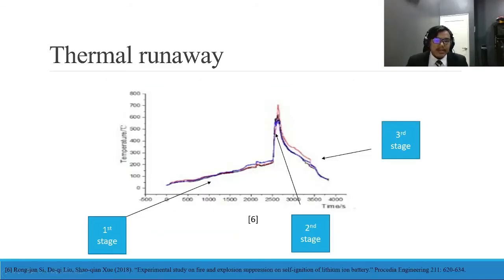This is a temperature graph for the thermal runaway, and as you can see, in the first stage the temperature rises slowly and continues to rise until about 200 degrees Celsius. Then suddenly the second stage takes over, and it happens very rapidly, reaching temperatures of 700 degrees Celsius and more. After that it gradually decreases because the third stage comes and the flames start to extinguish, and the temperature continues to drop until room temperature.